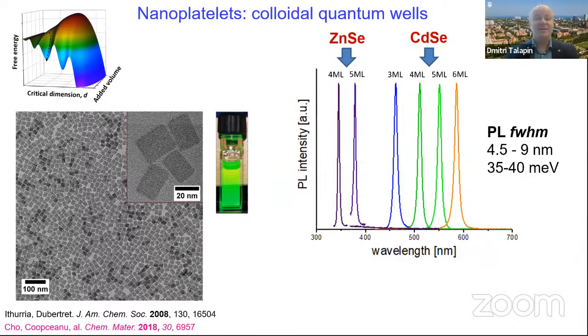And we can control the dimension or size of the structure with true atomic precision only along one dimension, the smallest dimension, the thickness. But in the system in the strong quantum confinement regime, it is the dimension that fully controls the electronic structure of the system. And as a result, we can make materials with very sharp ensemble emission lines.